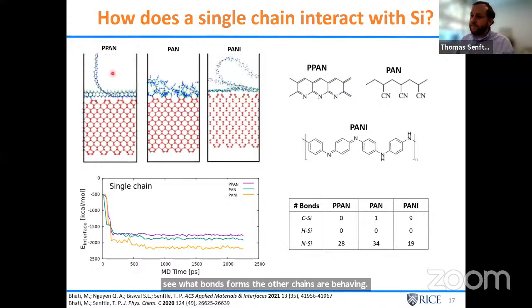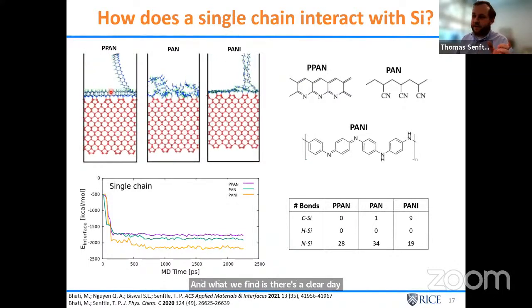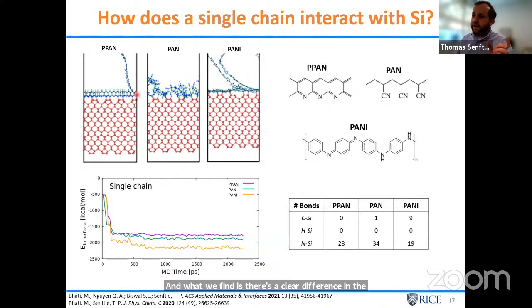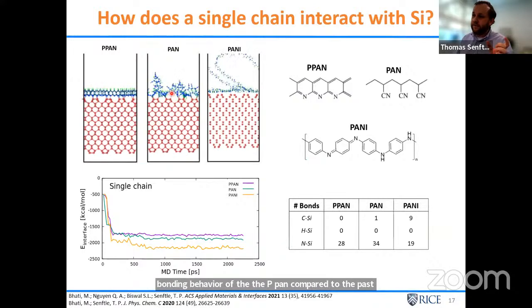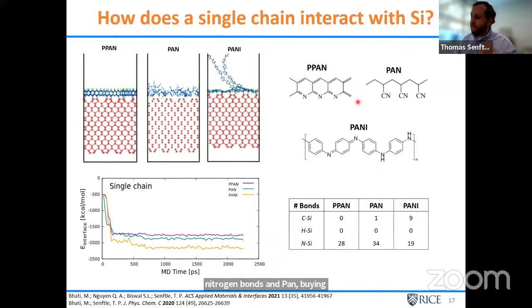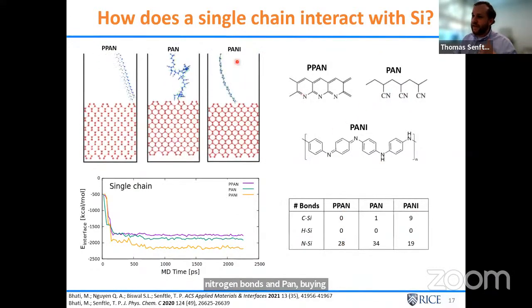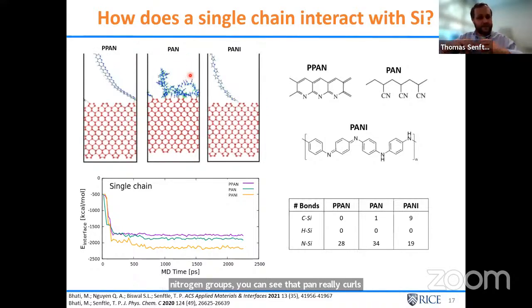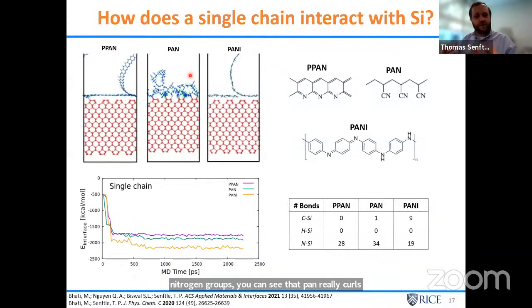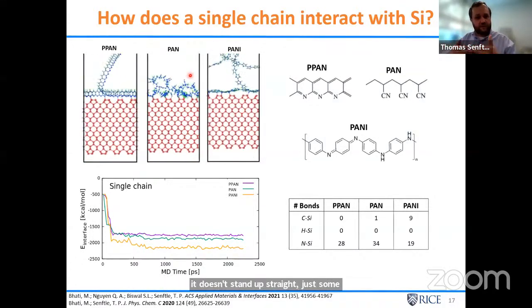And what we find is there's a clear difference in the binding behavior of the p-pan compared to the pan and the polyaniline. P-pan binds almost entirely through the nitrogen lone pairs, and it really stands up. Whereas the polyaniline lays flat, you have a lot of carbon bonds as well as the nitrogen bonds. And pan binds primarily through the nitrogen groups. You can see that the pan really curls up. It doesn't stand up straight, just some characteristics that we can observe about how a single chain behaves.